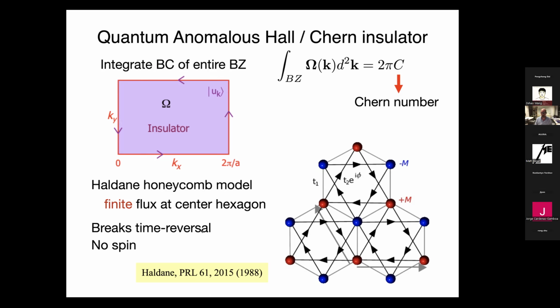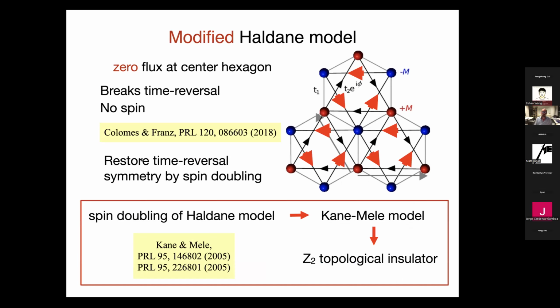This breaks time reversal and has no spin, so it's not an altermagnet yet, but we will now work to get it into an altermagnetic model. So we considered instead a modified model. The modified Haldane model is the same as before, but only the fluxes on one set of these triangles point in the opposite direction. So again, this breaks time reversal symmetry. There's no spin. And this model was considered first by Colomes and Franz in 2018.